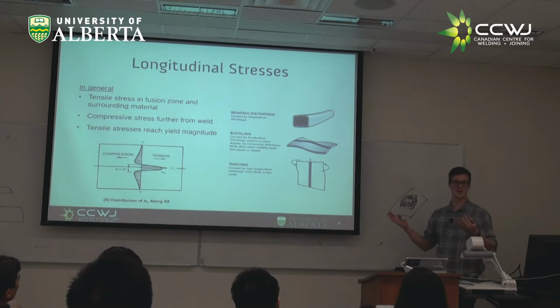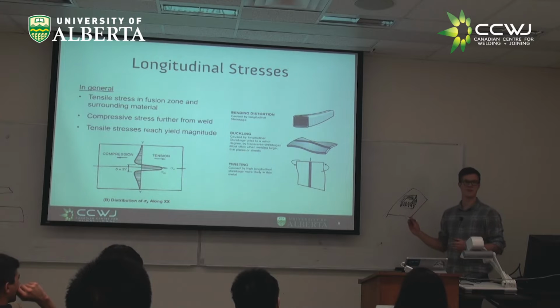If you imagine you're at a high temperature when you deposit that material, as it cools, it wants to shrink. So this plate is typically heated. Now what happens if you have a little bit of lifting of one corner is now it's no longer in contact with the plate beneath it. So it cools more rapidly in that area. And the whole thing ends up wanting to bend a little bit, and it lifts up a bit more, and it bends a little bit more, and it cools a bit more, and everything gets out of hand until your whole piece ends up looking kind of like a potato chip. And it's all related to residual stresses.